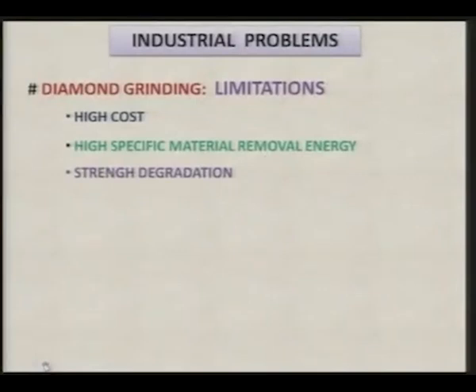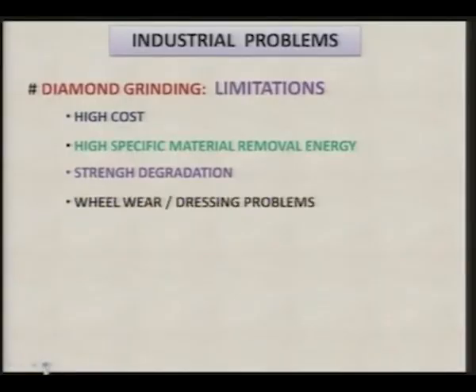As a result of the high amount of heat generation on the workpiece as well as on the grinding wheel, there is a degradation of the strength of the workpiece. Mainly micro cracks may develop, and thermal residual stresses in the finished component or machine components are observed. And due to the wheel wear, dressing becomes really a problem. As per conventional dressing of the grinding wheel, a large amount of abrasive particles or diamond particles are lost, and diamond grinding becomes quite an expensive and low productivity process.